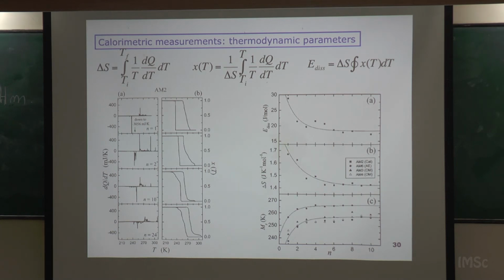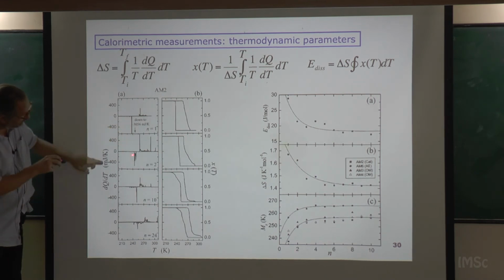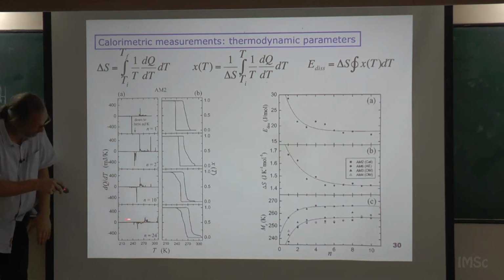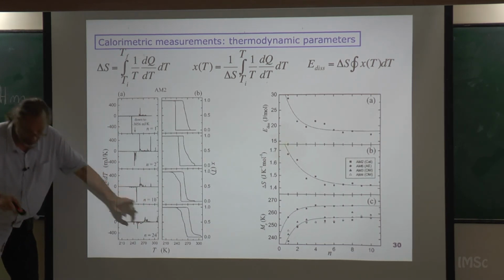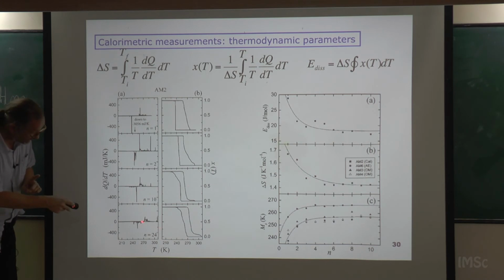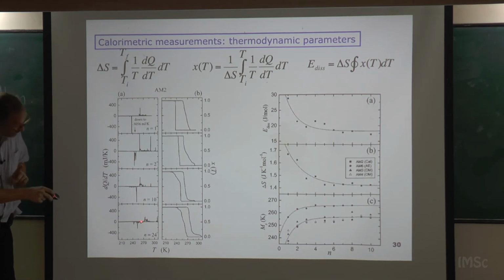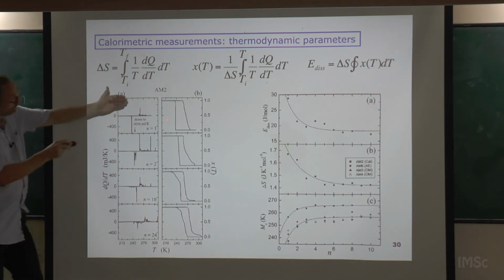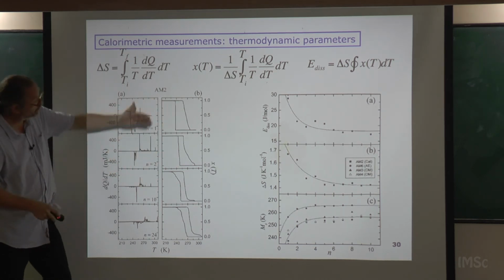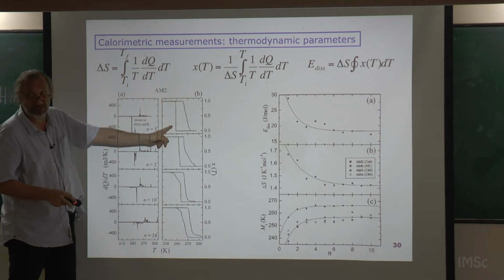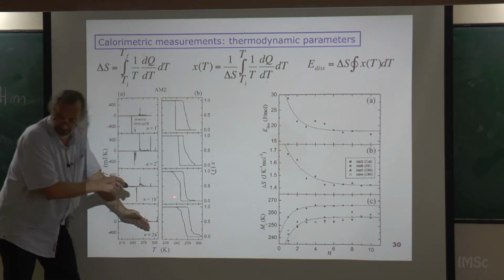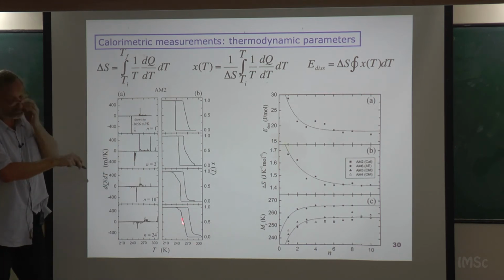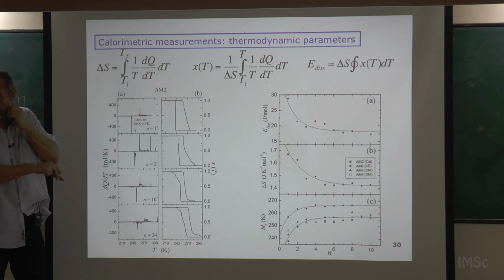When you do that, you can measure how the calorimetric measurements evolve with the cycling. You see that here, for instance, this one is very sharp, but then it develops some structure and it becomes something which has a certain structure. This is the width of the transition. So the transition starts here and ends here, okay? And when you cycle, it starts here and ends there. It widens, okay? And you integrate these curves, you get the hysteresis loops, which are this one here. This is the first time you have the transition, it's very sharp, but then it develops some structure here that you already see, but this is in calorimetry. You see that it becomes reproducible after cycling.